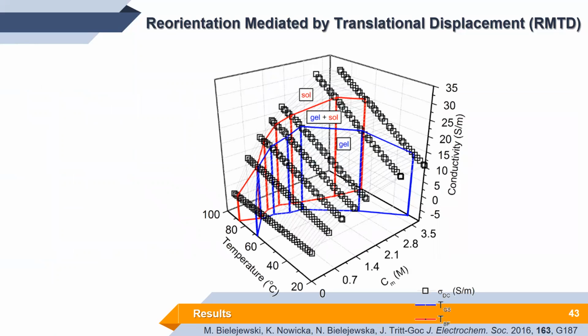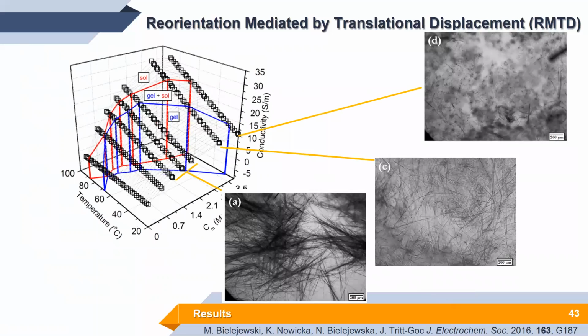But how to explain the increasing surface diffusion coefficient with increasing concentration of the ions? Well, this is because of the internal structure of the sample. It was quite specific and important for other reasons that when we created those systems, we always kept constant the concentration of the gelator to the fraction of water. So it was always like a 2% gel, LMWG molecules to water fraction. But when we increase the concentration of the electrolyte, then we increase the number of salt molecules and decrease the number of water molecules in the same volume.